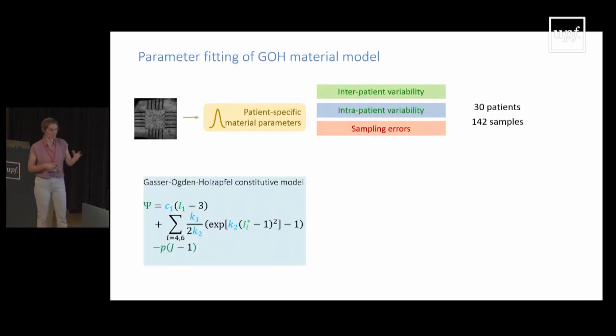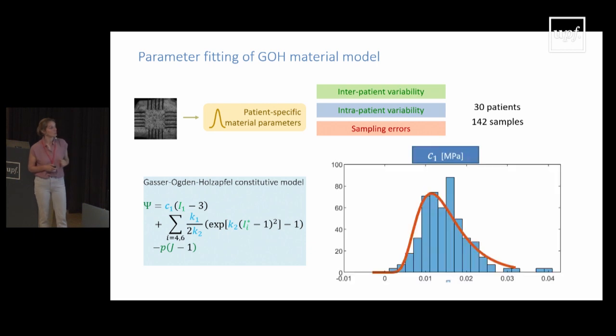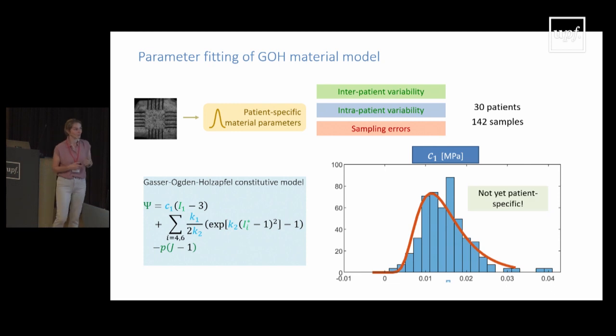And so then, once you've made all those decisions, you can do parameter fitting. In this case, for example, the Gasser-Ogden-Holzapfel constitutive model is the one we used. And here you can see, for example, for all the patients that we tested, the distribution for a certain shear modulus parameter C1, and then we fitted a log normal distribution on that, and that's obviously another modeling assumption that we make, but we're still dealing with the fact that we are using a retrospective database. So this distribution function is not very specific to the patient that I want to analyze and for which I want to check whether he or she is at risk for aneurysm rupture.